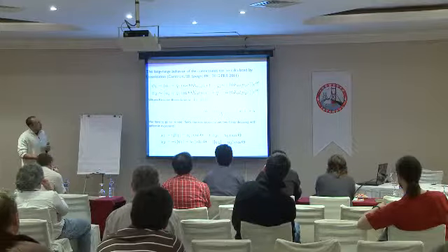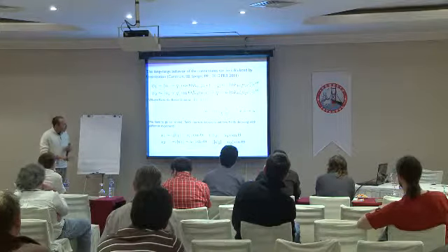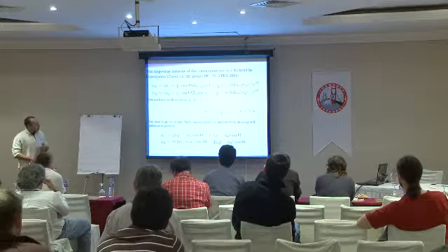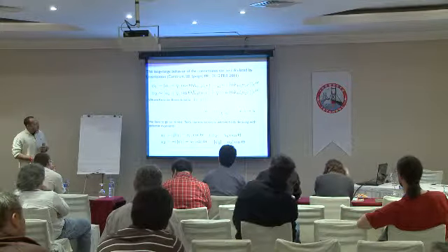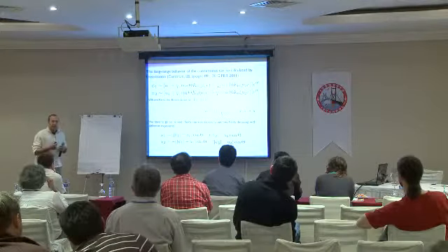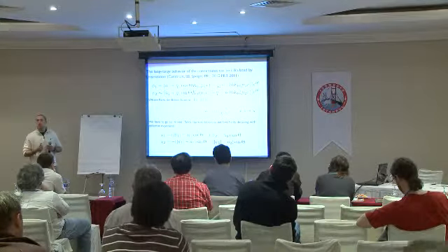The different exponents in each field will come with different prefactors, which we will call the mixing angle. We can parameterize it with some angle theta. So this is the basis function, and these are the exponents. However, if we redefine our fields, representing them as linear combinations of our original fields, we can always find two linear combinations, each behaving according to a single exponential law.